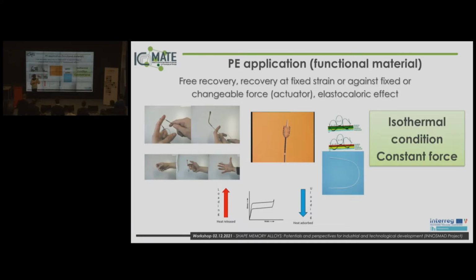And then the first possibility is to use this material as a principle for a refrigeration system. From one point, the material absorbs heat, and from another point, releases heat. We can use the material like the gas compression system. When we increase the pressure of the gas and we release the compression of the gas, we have absorption and release of heat.